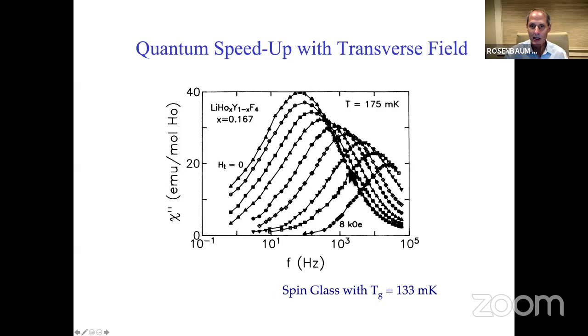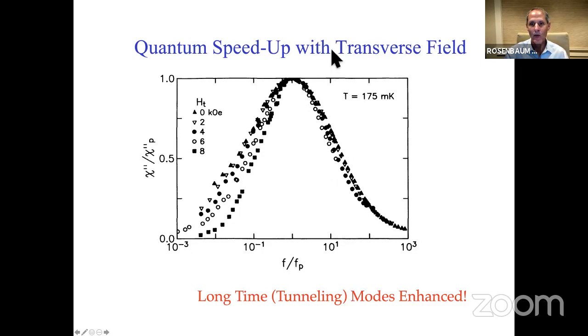Now, the interesting part of this that you can see of how this is working, and that's largely quantum, is if I take these curves now and I scale them on top of each other. So the next graph I'm going to show you is scaled by the peak frequency of each of these, and then the maximum. Okay, so that's this plot here. What you see is that this is the peak frequency being 1. And now on the high side, the fast relaxation, basically they all look the same. But as I change transverse field from 0 kilogauss up to 8, these long time, low frequency tails are pulled in. They're pulled in and cut off because there's tunneling through the free energy surface. Okay, so that's the effect of that.